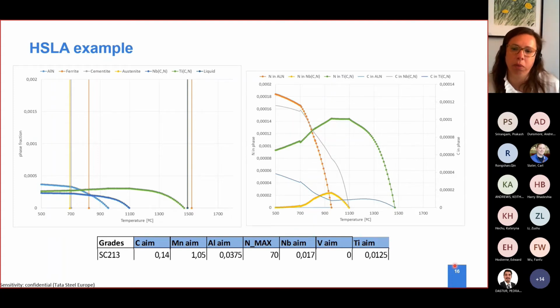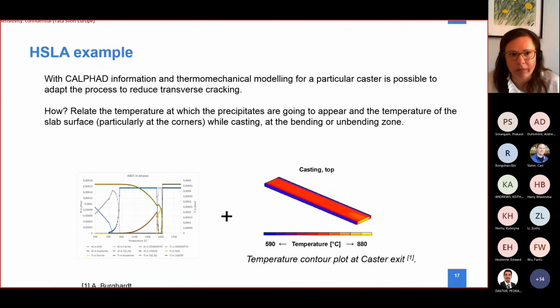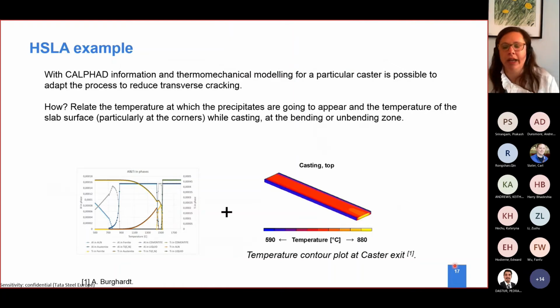What we get here is the complexity that we cannot get from a simple carbon equivalent formula or a simple phase diagram. We need to go deeper and try to understand all these interrelations. If we know when these precipitates appear, at which temperature, and more or less their composition, we can combine that with an FEM model of the temperature of my slab, and know exactly which temperatures we should avoid in the bending and unbending zone.